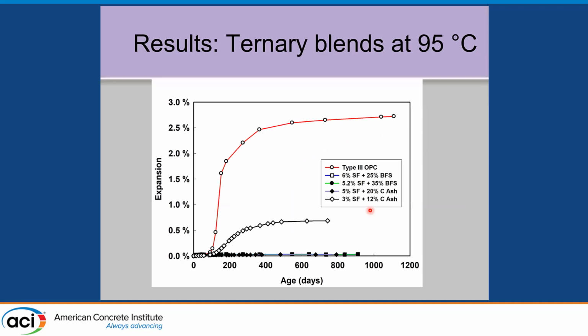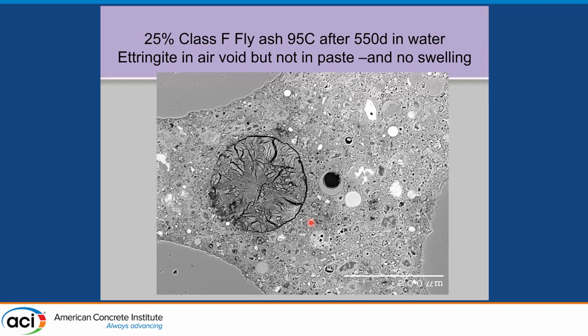And ternary blends, these are slag and silica fume mixtures and silica fume and fly ash mixtures. And the one with very little silica fume and not enough fly ash didn't control it sufficiently. So we're seeing this effect of the SCMs with aluminates are effective for the most part.